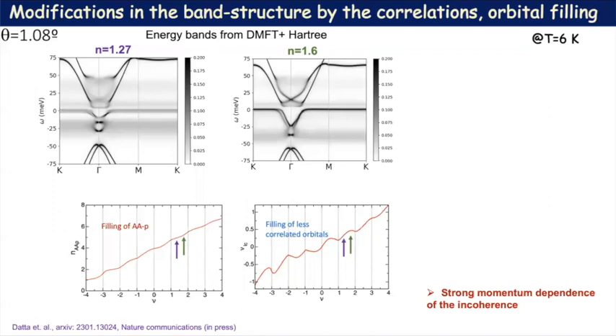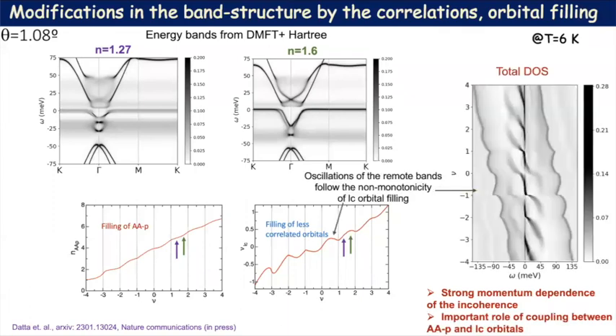So there is a repetition of the same thing, where the AP orbitals are becoming incoherent and we have a filling, and the less correlated orbitals are getting filled until the upper Hubbard band comes to the 0 energy. And this continues with doping. So we have this filling of correlated and less correlated orbitals periodically because of the coupling between these two types of particles. Now you can see that the non-monotonicity of this profile is similar to these oscillations in the remote bands that we have in this cascade picture, and that's because the energy associated to this band is proportional to the filling of these orbitals. So the upshot is that along with the correlation in the AP orbitals, which are the correlated orbitals, the coupling between the two orbitals is also important to have these cascade features.